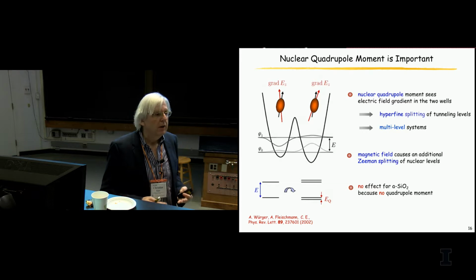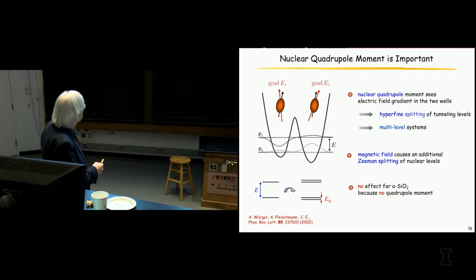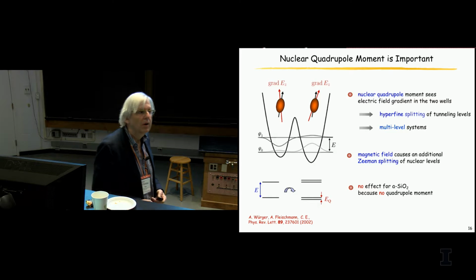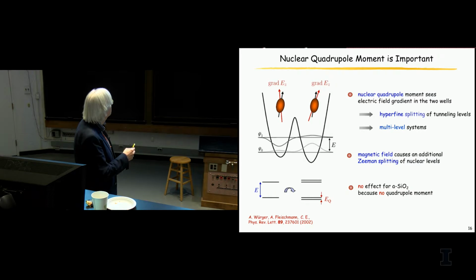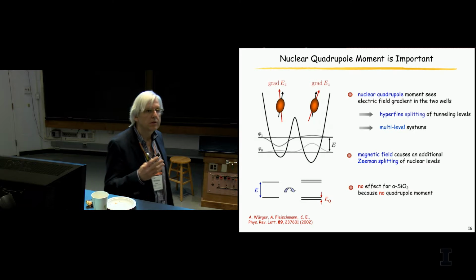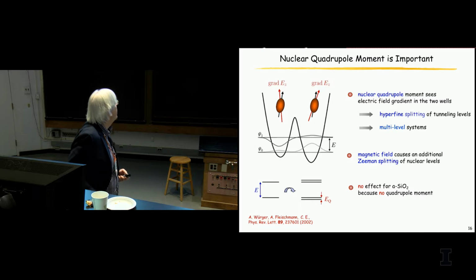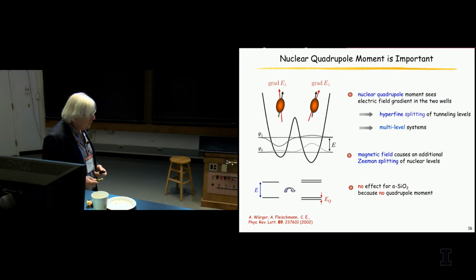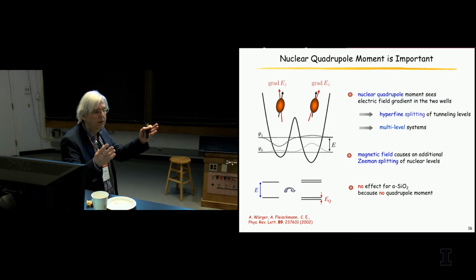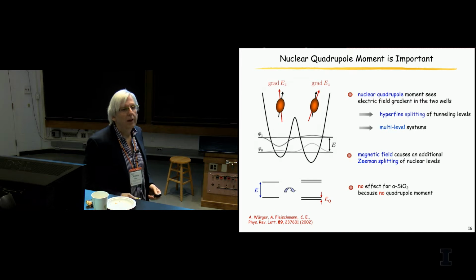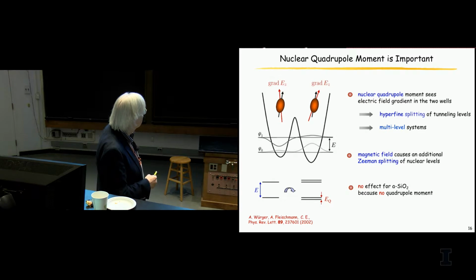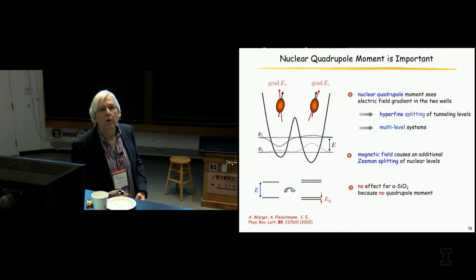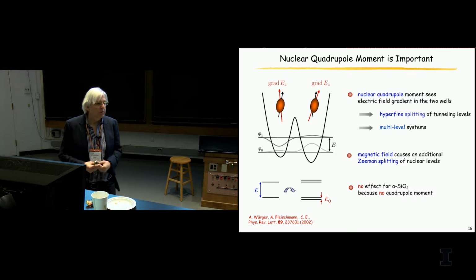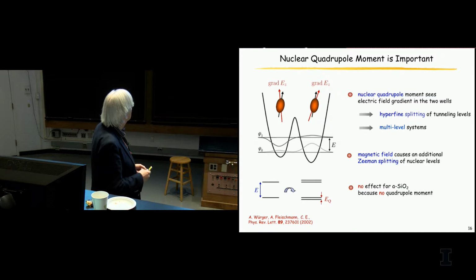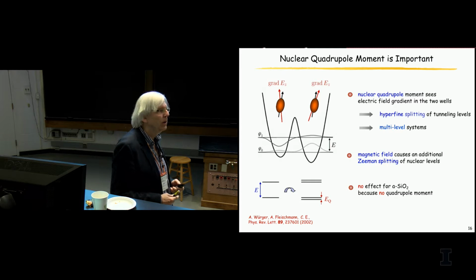Or you can say simply you have a hyperfine splitting. Your 2-level system becomes a multi-level system. And the splitting here is the splitting what the nuclear quadrupole produces in this electric field gradient. Now, and then if you apply a magnetic field, of course, you Zeeman split those levels, and you can couple to the 2-level system directly. Now, it's already clear for SiO2 this is not happening because there is no atom in it which has a nuclei with spin larger than 1/2. Yeah? So there's only dipoles in there. Therefore, this was already a strong hint.